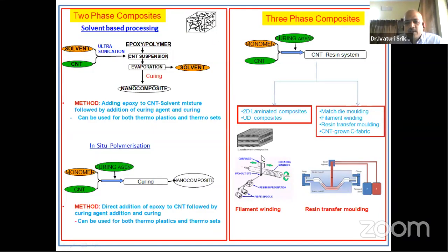The actual applications should deal with carbon fiber reinforced epoxy. Take that as a benchmark, add the nanotubes into the resin system, apply that onto the carbon fabric, and prove the improvements over the conventional carbon epoxy composites. So this is how it is made. You mix the CNTs into the liquid resin system, apply that CNT added resin onto the carbon fabrics, as shown, then lay up the carbon fabrics, compact and cure. There are other processing methods also. What I have shown is a simple laminated composite, again made at a lab scale to study the preliminary possible improvements.